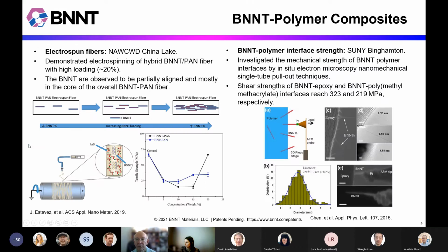And then to move on to polymer composites, we have a collaborator with the Navy out in China Lake, California, who's working on electrospun fibers, particularly PAN, which of course is a precursor to carbon fiber. So they're working on using a unique dispersion method to get the loading of the nanotubes up in PAN and then to electrospin that. As you increase loading in something like a fiber, you get more tube-tube interactions, and you're going to have a higher strength fiber that is going to be able to display more of those favorable properties of the BNNTs rather than having all these voids, as you can see here.